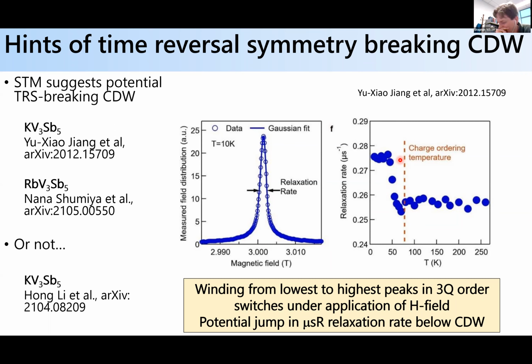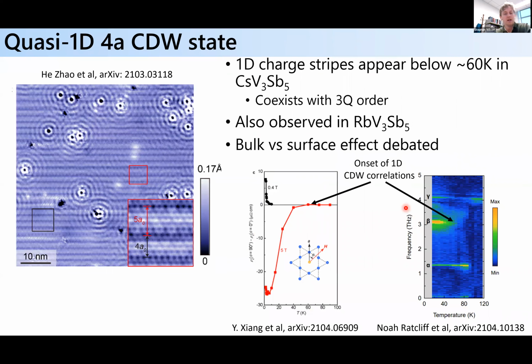Okay, so it's kind of like it makes the muons oscillate, and then they look at the relaxation rate as they oscillate on cooling. Okay, and so basically they see a jump in this relaxation rate as you cool below this, and this is under an applied field of a couple Tesla. Okay, so it's maybe hinting that there is some type of coupling below the CDW. In isolation, maybe it's not too profound, but coupled to the STM data, it's maybe a nice kind of supporting piece of information.